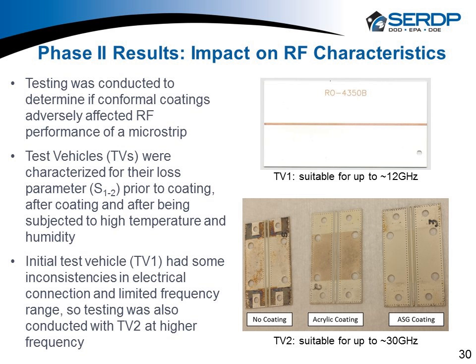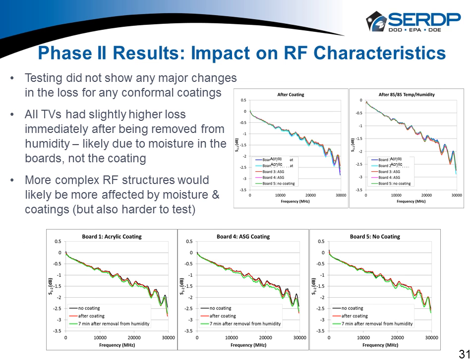So we had a couple different test sets here. One of the vehicles we tested up to about 12 gigahertz, and the other one we tested up to about 30 gigahertz, looking at what would happen with signals in those ranges. If I go to slide 31, you'll see I'm not a Sparky, I'm a material engineer, so I don't quite understand these graphs very well, but what they tell me is if the coating was impeding the signal, you would see spikes in here. You would see differences across the signal for the different types of coatings. And for the most part, the signal without the coating and the signal with the coating are all on top of each other. So the application of the liquid glass ASG coating didn't change how the RF signal was propagating down those test vehicles on their signal lines.